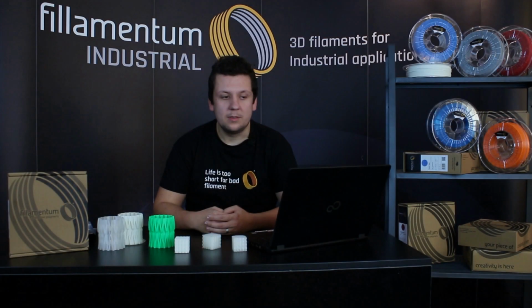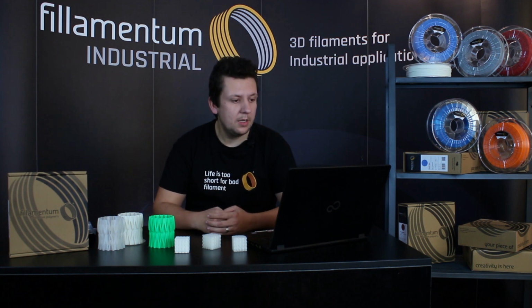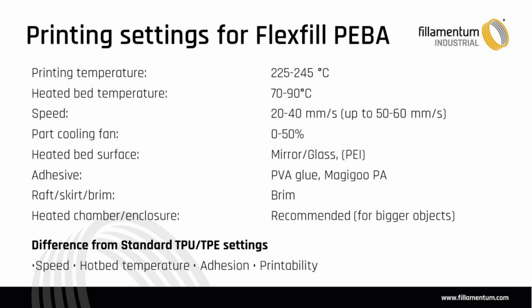And now is the time for the new member of our Flexfill family. It's Flexfill PEBA. PEBA stands for polyether block amide. You can see the print settings for this material. So the printing temperature is 225 degrees Celsius to 245 degrees Celsius. What is different from the basic TPU or TPE Flexfills is the heat bed temperature. It's 70 to 90 degrees Celsius because of the polyamide in this material.